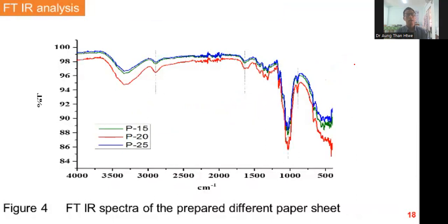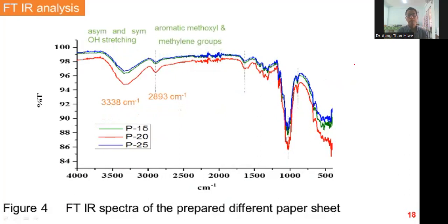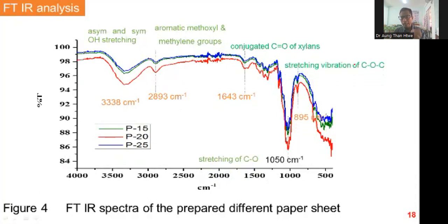Now let me continue with the FTIR analysis. As in the figure, every aspect of the different paper sheets is shown. The first one, 3338 per centimeter, is attributed to asymmetric OH stretching vibration. Another one, 2893 per centimeter, is attributed to aromatic methoxyl and methylene groups. The third one, 1643 per centimeter, is attributed to C=O or C=N, and another one, 1050 per centimeter, shows C-O stretching vibration. And finally, 895 per centimeter shows stretching vibration of C-O-C. This is the characterization of organic compounds in the natural fiber.